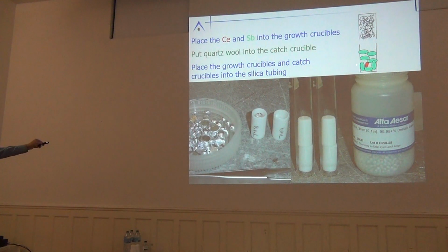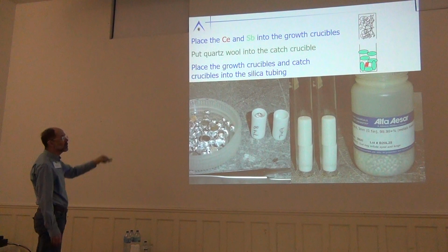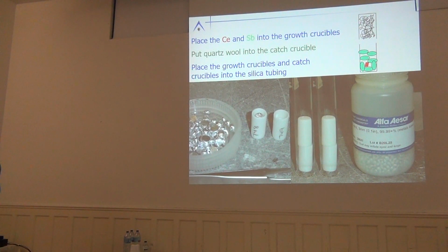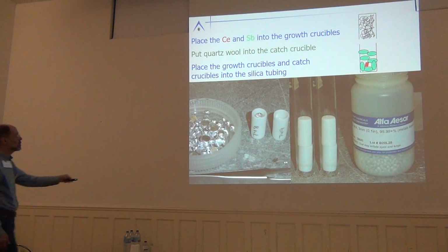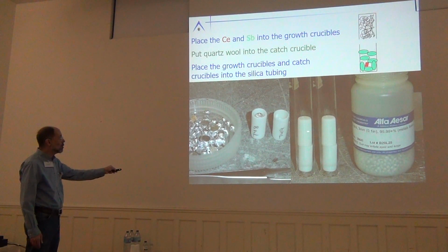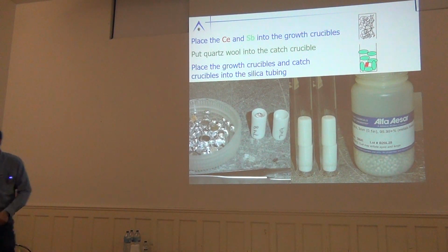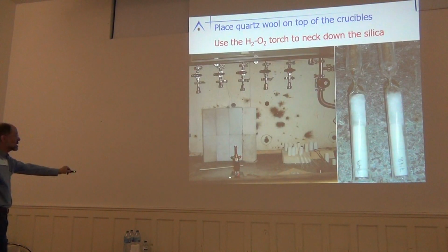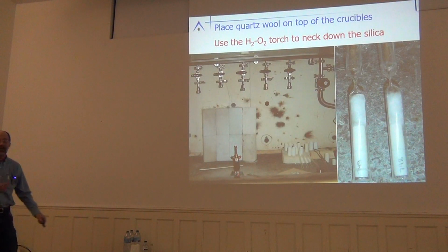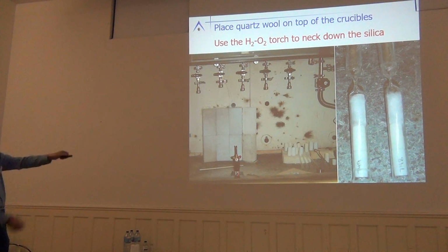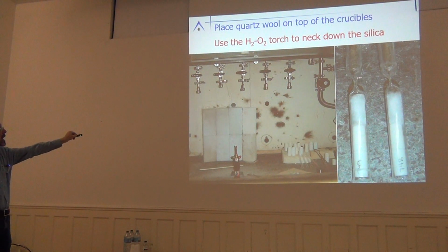I can pack my elements, my antimony and my cerium, into a crucible. I have a second crucible that I put a bunch of quartz wool in, or in some cases I have a little filter here that will help me separate the liquid from the crystals once I'm done with the growth. I have my elements down here. I have my quartz wool up here. And now I'm going to take these to the glass bench. This is a hydrogen-oxygen torch. It's a very hot flame. I can put the tube in there. I can manipulate it. And I can put an hourglass-like neck here, so I can still pump through this, but it will be easy to seal.